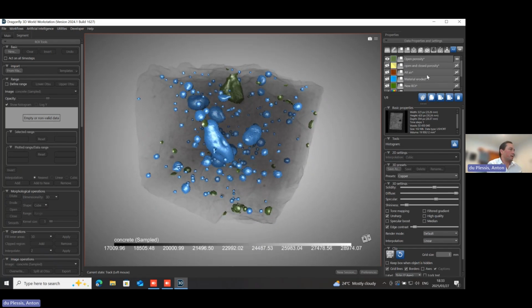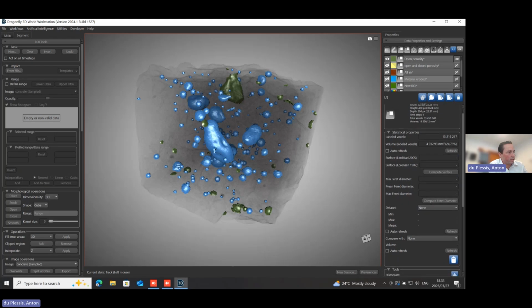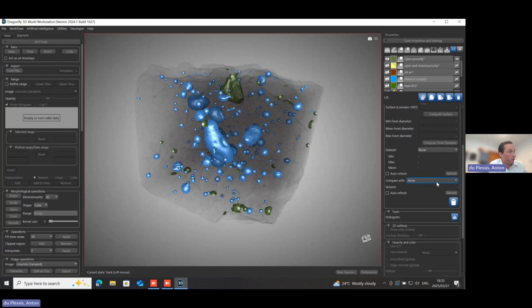And the nice thing here is if we click on the material region of interest, we can also get the percentage fractions. So you can now compare the material with closed porosity. This is 2.02%. And with open porosity, it's 0.38%. That's also why I wanted to go through this exercise. It's also relevant to other cases where you have segmented something and you want to get the relative volume fractions. So that's everything that I wanted to show on that sample.